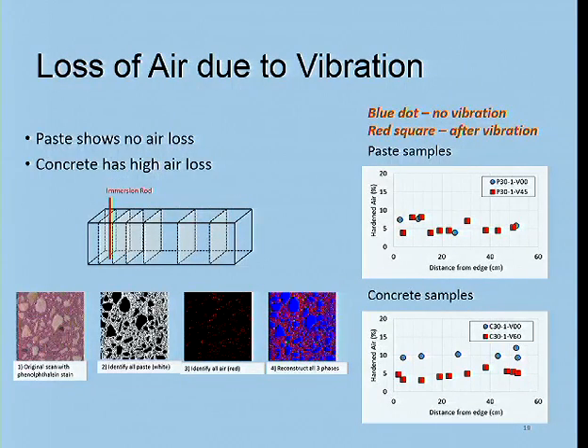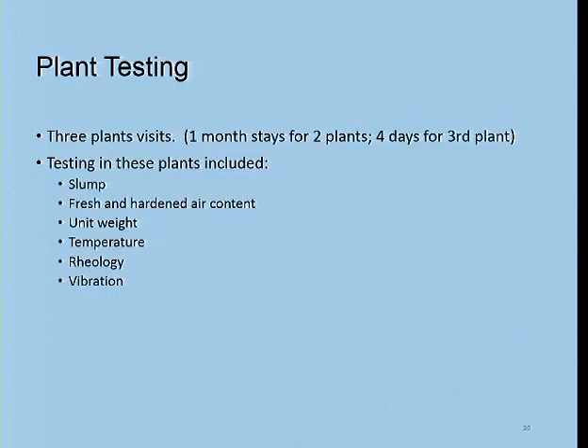Another thing we were able to do in those kind of experiments is measure the air loss at different points using our image analysis technique. And the point that we want to make on this chart is that, again, the paste samples that were vibrated have essentially the same air before and after vibration, but concrete before vibration is about 10% air, after vibration about 5% air, and so this same result is being expressed there. We also had a chance to go to the plant. Actually, KSU students were involved in these plant visits, 1 month stay for 2 plants and 4 days for a 3rd plant.